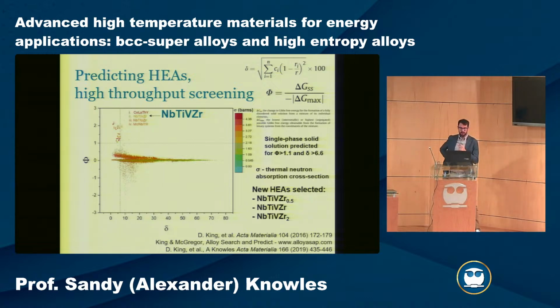For him, he was looking at methods which are effectively akin to the Hume-Rothery rules for whether elements are likely to mix together. So we have one of the parameters, which is just the atomic size mismatch. If elements are very different sizes, they're probably less likely to want to mix together. And he then developed this phi parameter, which was trying to predict the entropic stabilization, so trying to predict entropy. And when we take this, this code is really nice. It is technically publicly available, but I think the website link died, but we have a copy of it if anyone wants it.